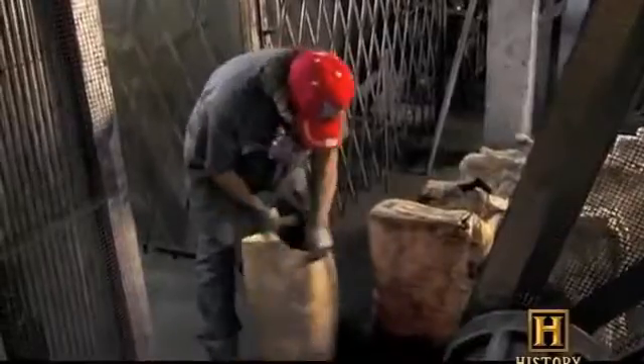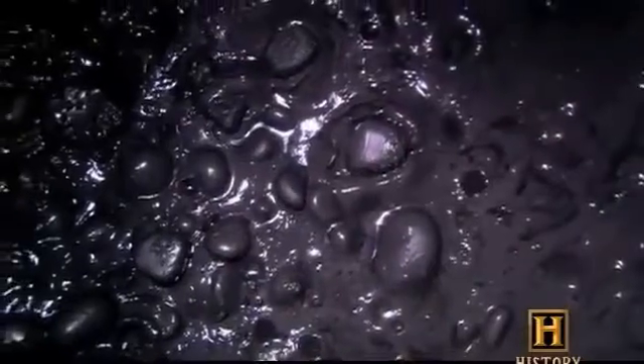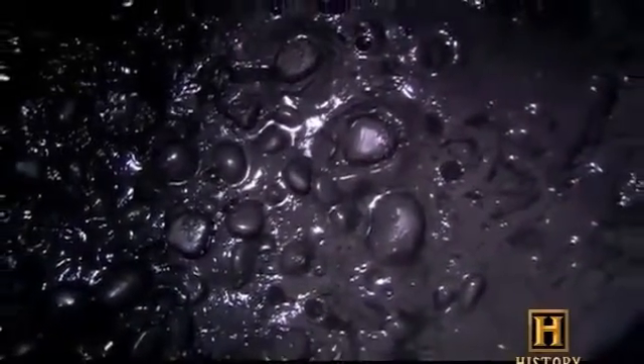Making a pencil begins with a mixture of graphite, carbon powder derived from coal, and a smaller amount of clay. Increasing the percentage of graphite makes for a softer, darker mark, while more clay makes a harder, lighter mark. A 750-pound mix of graphite, carbon, clay, and water is fed into this ball mill filled with river stones. The ball mill churns the ingredients for 24 hours until they form a smooth, homogeneous slurry.